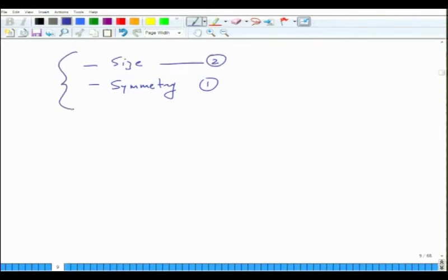So, now you can see, we have seen why we do not have 28 Bravais lattices, why we have only 14 Bravais lattices, and the reason lies in symmetry, that some of them can be represented either by higher symmetry structures or by smaller size unit cells, or in some cases they do not represent the symmetry of the crystal system at all.